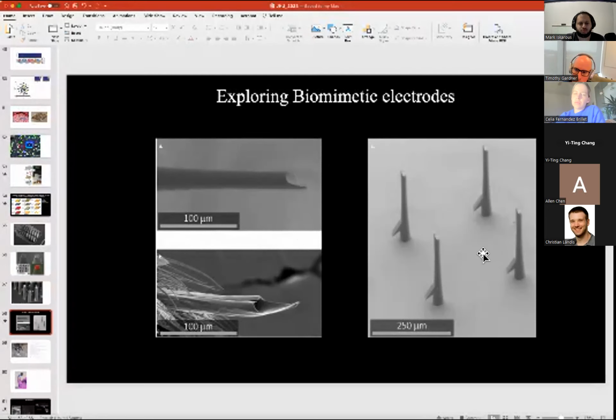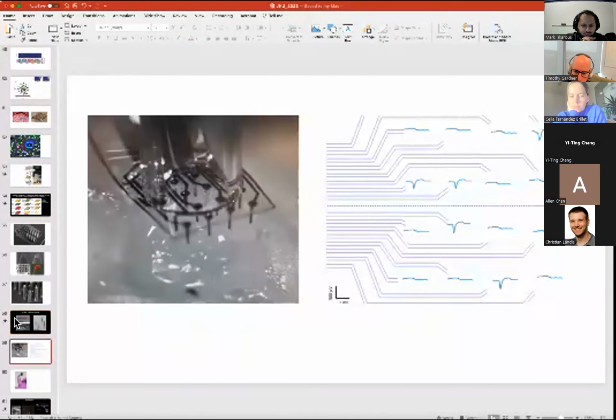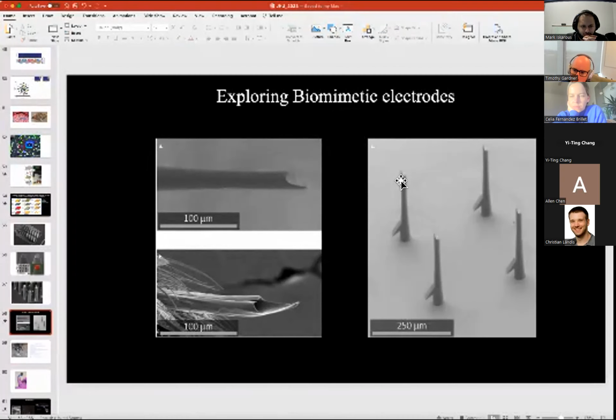and we haven't worked this out completely yet. But one of the variations that we were able to print, these were electrode spikes that have a little sharp protrusion at the tip that was designed to mimic the structure of a mosquito proboscis. And these arrays we found could actually be implanted in small animals, mouse and bird, going through the dura. So we didn't even have to dissect away the dura, but could just take that thin film array, lay it on the surface of the brain, and then push on the backside and get it through the dura. We haven't yet made functional tips with that particular sharp feature, so we'll need to open a contact point on the side while still preserving that sharp tip. And I'm optimistic that we'll be able to do that, but it hasn't been completed yet.